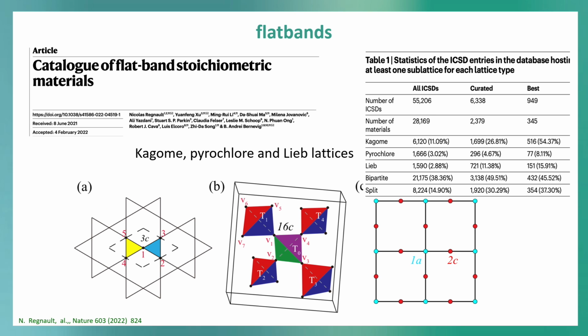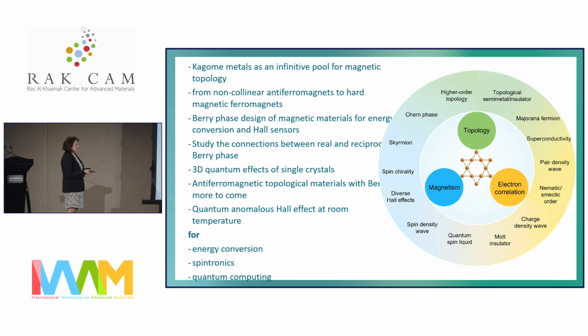Anyway, this is only the beginning of the search for flat bands, so people are now getting crazy about flat bands. There are also the pyrochlore lattice and the Lieb lattice, which allow for flat bands, and we did some systematic investigation to look for flat bands, because Andre thinks he finds a room temperature superconductor there. I don't think so, because I'm a chemist. Flat bands make everything dead. You need some dispersion, but it's really a nice playground, I think, for seeing interesting properties in these materials. I hope I gave you a little bit the impression that you can find a lot of interesting stuff there. And since there are at least 999 unexplored compounds where German solid-state chemists made the compound but never measured even the transport properties, they probably didn't find anything like charge density wave instabilities, etc. There's still a lot to do and interesting stuff to find in these compounds.